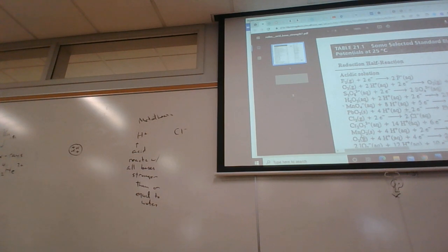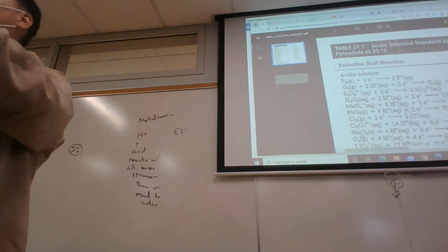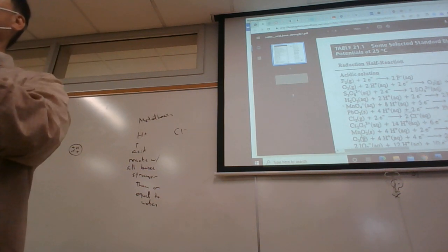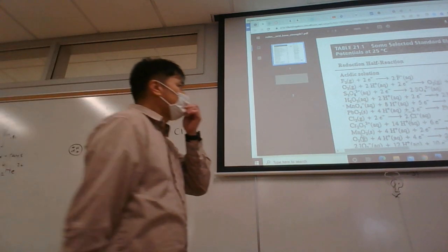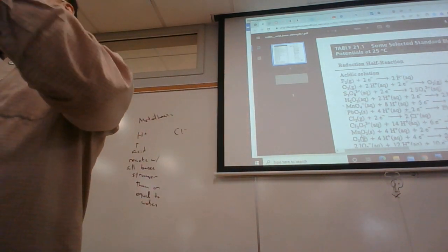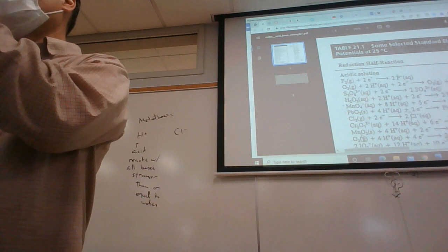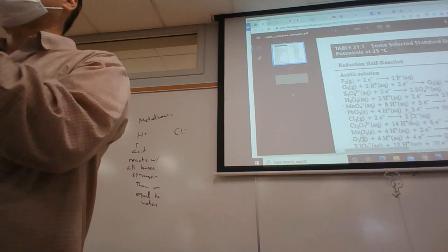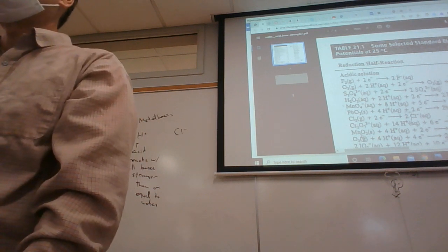In terms of oxidizers, I used to work with fluorine when I was at UCLA. When I worked with fluorine, I used stainless steel lines. The fluorine would eat up the inside, but it would form a barrier layer, what we call a passivation layer or inert layer. And so the stainless steel was okay, except for the valves. I had a gas line with a lot of valves, and the valves had a Teflon seat to close them. The Teflon would be eaten up by the fluorine gas, so I had to replace the valves maybe once a week or once every 2 weeks.